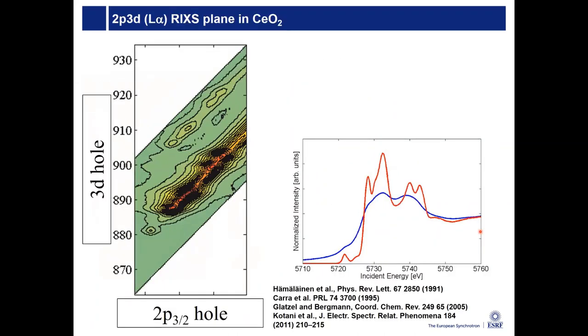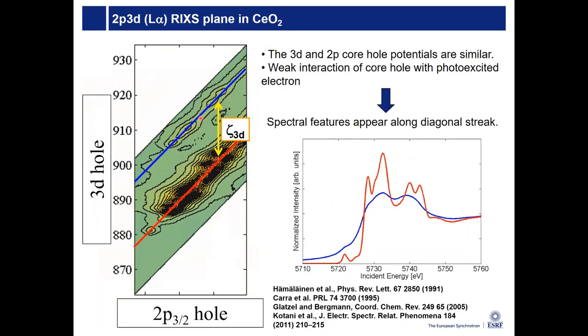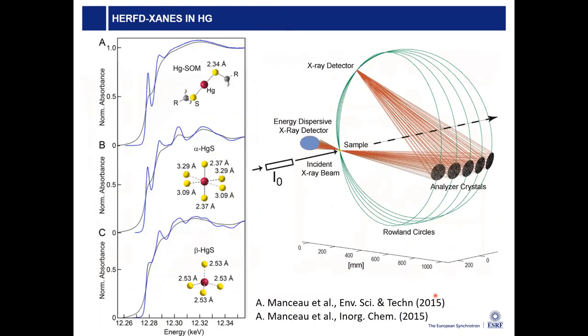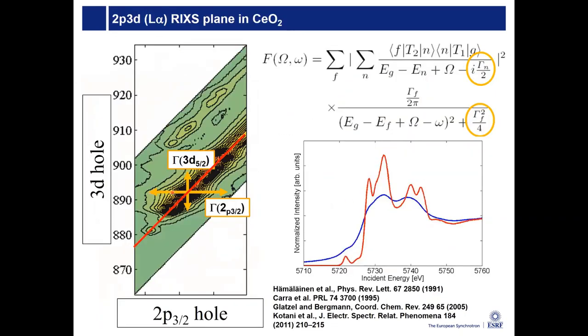Okay, and this shows again, so you have a 2p hole in the intermediate state, a 3d hole in the so-called final state. You see this spin orbit splitting of 3d levels here, and again you see this broadening that I showed before. It was done a long time ago actually by Hämäläinen already on dysprosium in 91. So I just explained to you here where this actual broadening comes from. The lifetime broadening of the intermediate state stretches in this direction, lifetime broadening of the final state in this direction. And I can do a cut through this RIXS plane at 45 degrees relative to those broadenings. And that gives me the spectral sharpening.